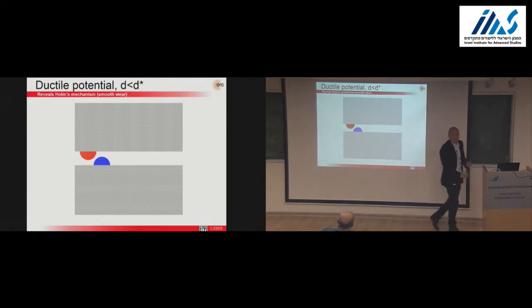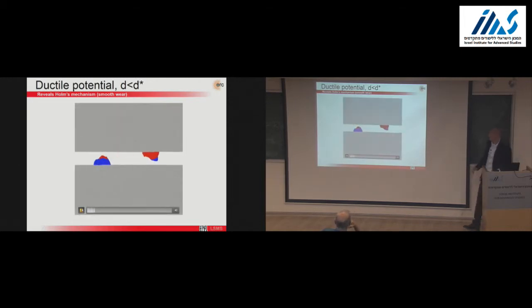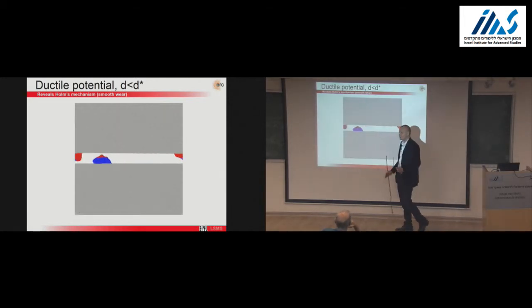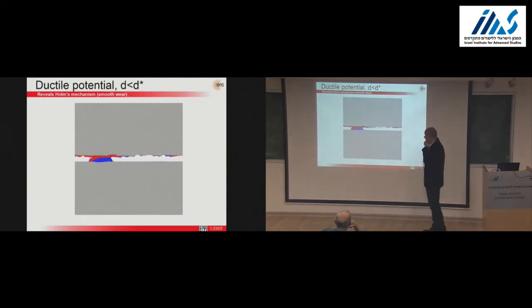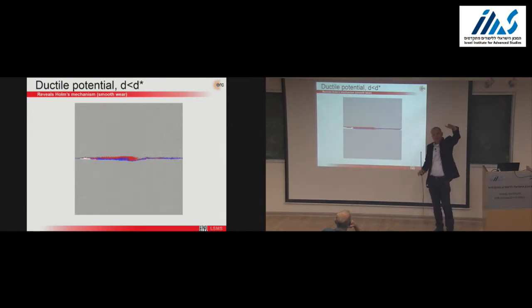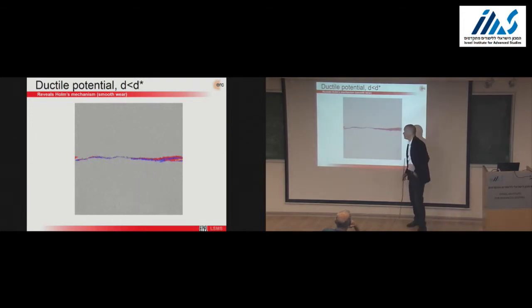So we expect Holm's mechanism. And that's what we get. So it's consistent with the theory. You see we've got some exchange of materials because there's adhesion. And because we maintain a constant pressure P, well, the space is closing, and at the end you form, let's say, a grain boundary. Okay?